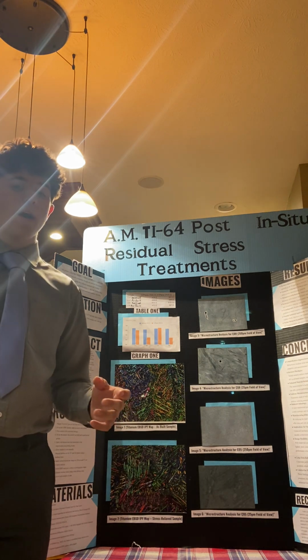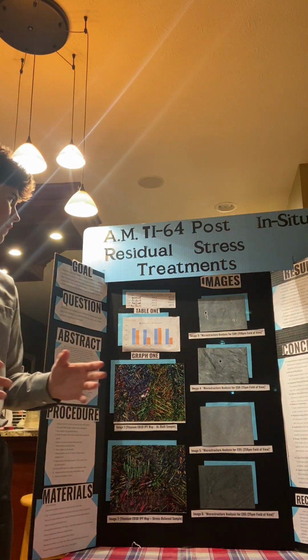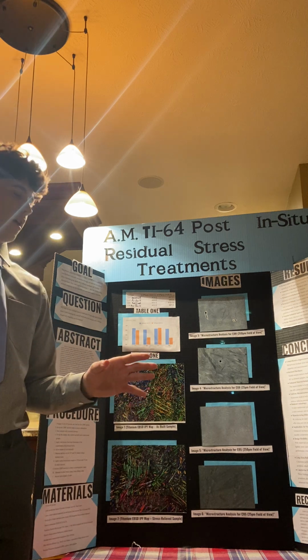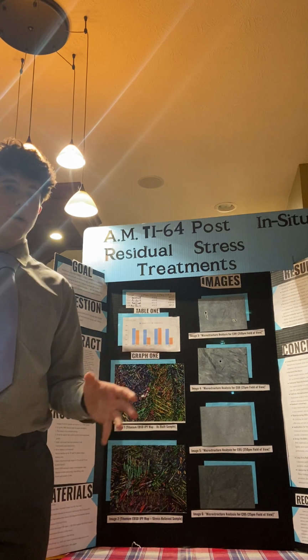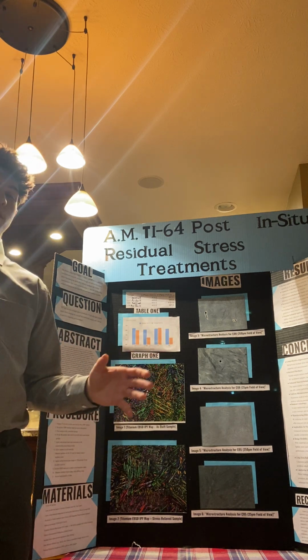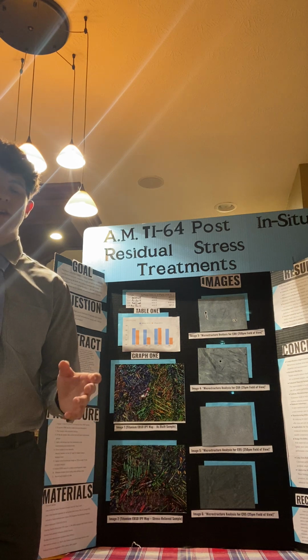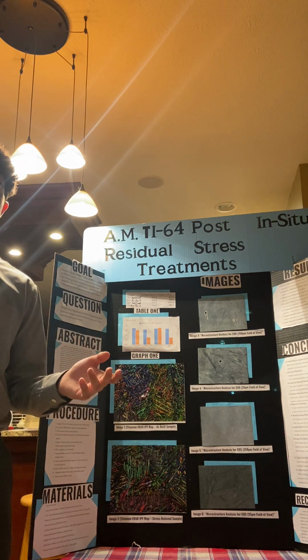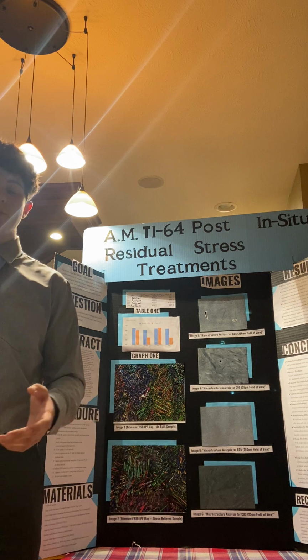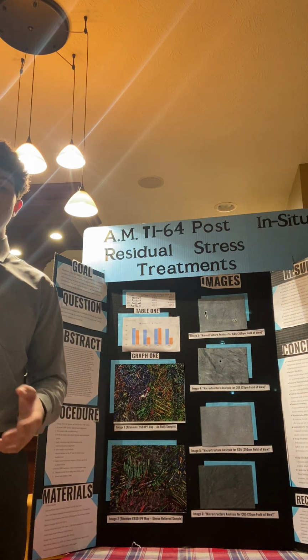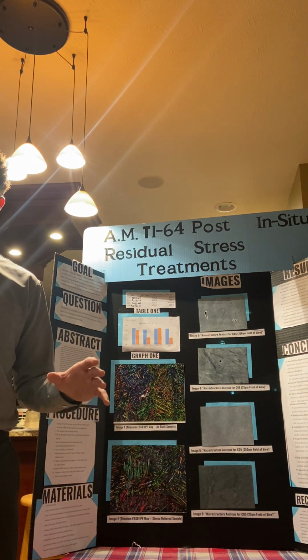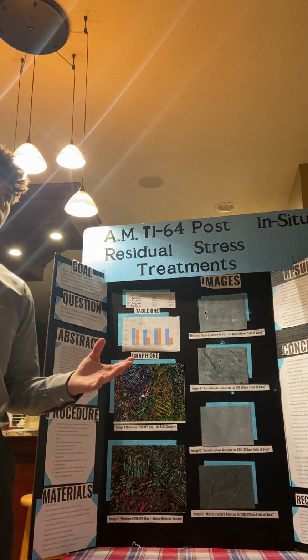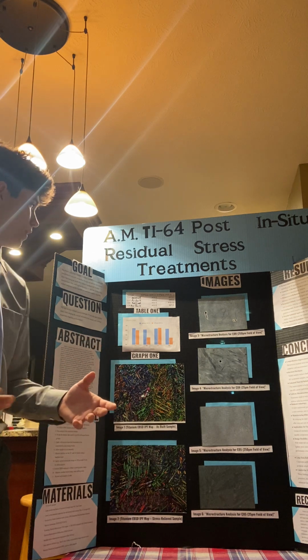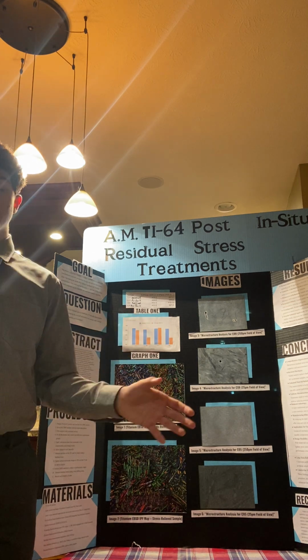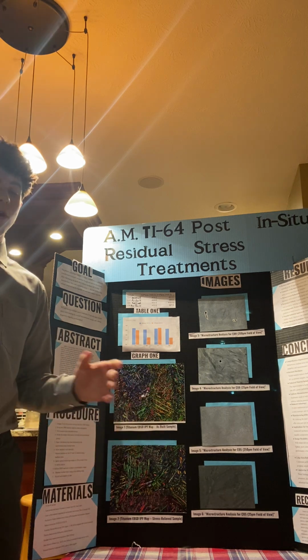So with this one, I had two specific materials. I had 4 samples. So CO1 and CO2: CO1 was the relieved sample, the stress relief sample, so the experimental group, and then CO2 was the as-built sample, the control group, which had no residual stress treatment done to it. And so CO1 was the stress relieved, so the experimental group. CO2 was the control group.